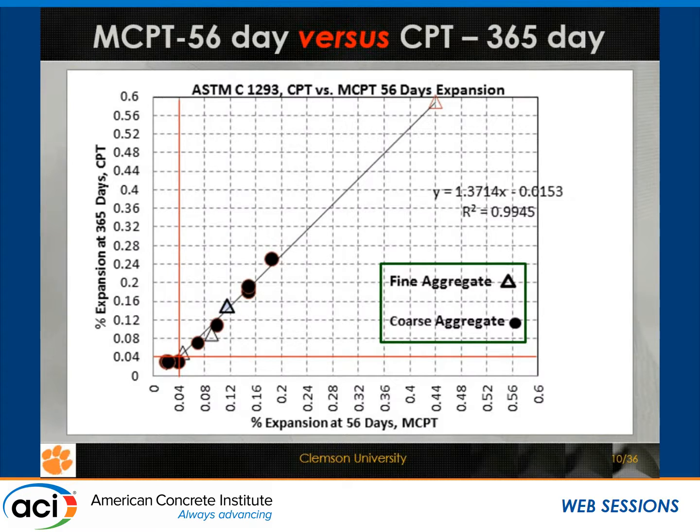that basically the MCPT at 56 days correlates really well with the concrete prism test at a year, and both coarse and fine. But when we selected these aggregates, a lot of these aggregates were either highly reactive or non-reactive. We had a very few that were in between.